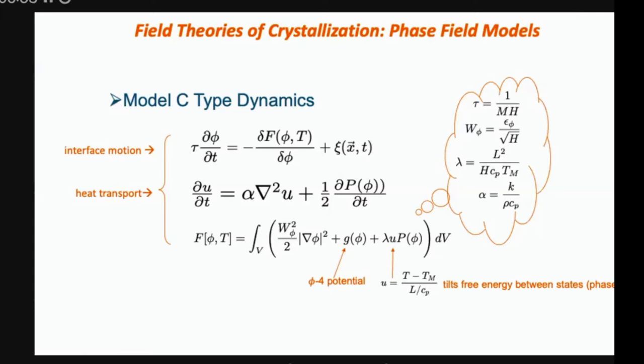And to be sure, there's a bunch of parameters that enter this equation, a time scale, an interfacial scale that separates the zone between the two phases, solid liquid, a coupling constant, which is inversely proportional to the barrier to nucleation, plus other things like latent heat, thermal diffusion, temperature, and a thermal transport coefficient alpha, which is proportional to the diffusivity.